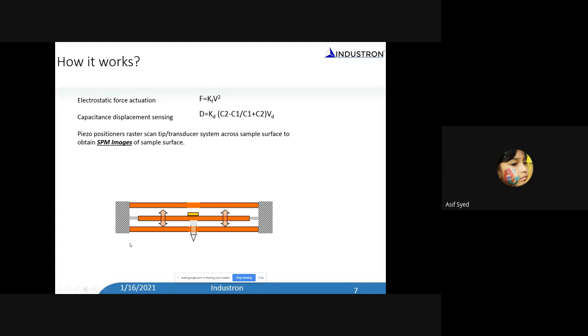and it's all a precisely manufactured transducer. In this equation, if I apply a voltage, the force generated is proportional to the voltage squared, times a constant. It's as simple as that. So as long as I know the voltage that I apply, I can calculate the force. Similarly, for the displacement, it's a change in capacitance. You can measure the change in capacitance in terms of voltage, and then convert that into a displacement. So this is a very simple way of applying the force and measuring the displacement.